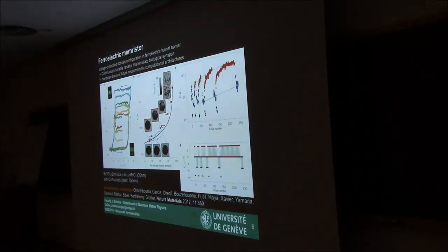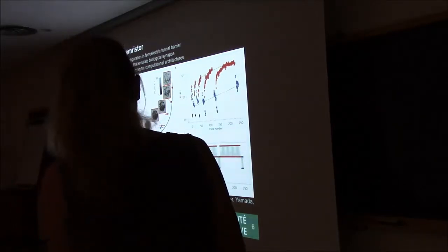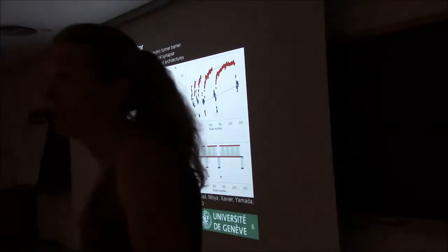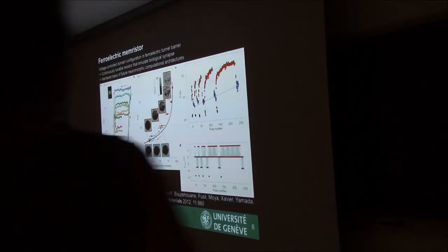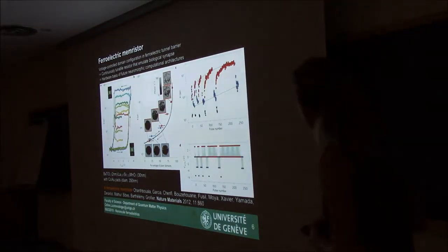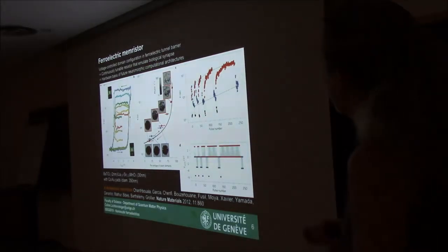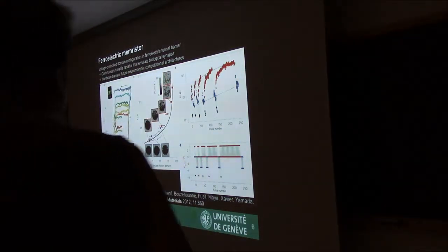And now by switching the polarization, you change the resistance of the LSMO. And so here you see that you can get a very large change of the resistance, and you can repeat that for many pulses. Before we were talking of a change of an order of 3, here it's a change of 2 orders of magnitude in the resistance. So this can also be used as a continuously tunable resistor that emulates a biological synapse, and it can be seen as the hardware basis for future neuromorphic computational architectures.